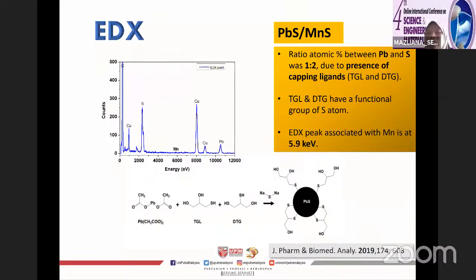To further confirm the presence of manganese, we ran EDX. We found that the percentage ratio between lead and sulfur was 1 to 2, so sulfur is higher than lead. This is expected because the sulfur percentage is doubled due to the sulfur in the ligands themselves, the thiols that we use, and also the sulfur that we add during the synthesis. This is the EDX of the core-shell sample 0.3, and we can see an EDX peak at 5.9 keV, which corresponds to the presence of manganese.